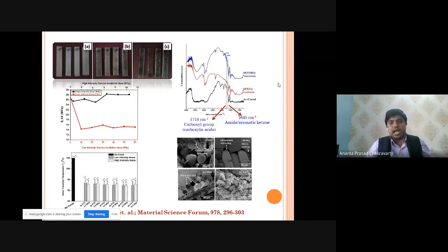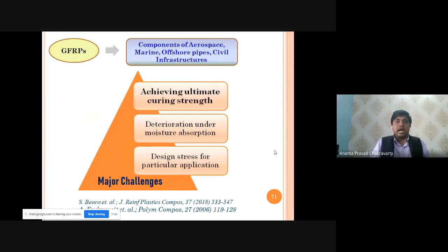Then I went for FTIR analysis, Fourier transform infrared spectroscopy, and in that, at a certain wave number zone, some additional oligomers appeared. Oligomers means small molecular weight polymers. These are formed with amide and ketone groups, and they help a lot with curing. Hence, at the high intensity dose, you can see all the fibers holding together and fractures are fewer. But at low intensity dose, you can see fibers getting delaminated and matrix failure. These components are also very important in achieving ultimate curing strength.